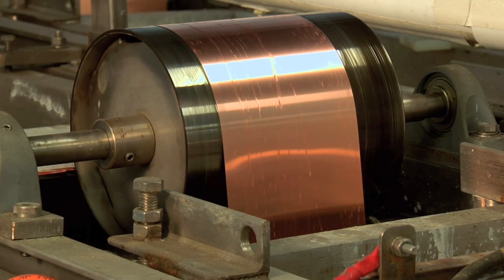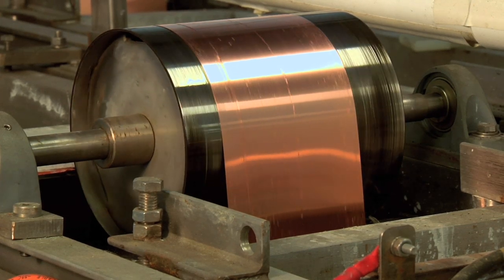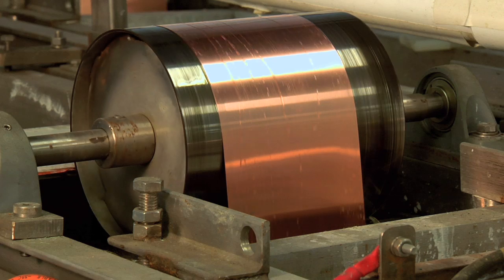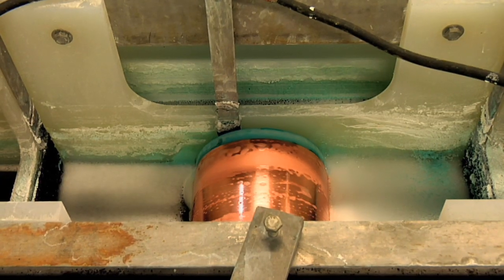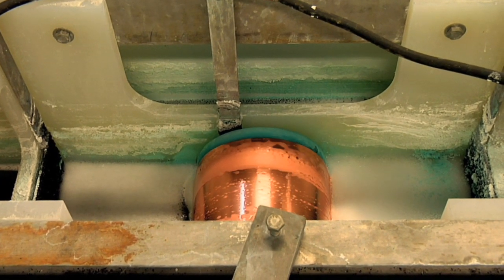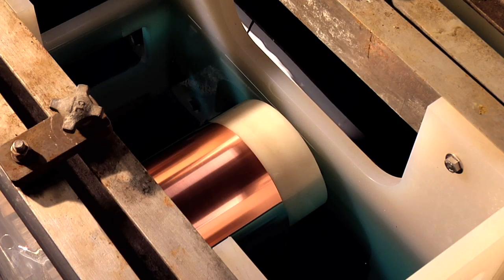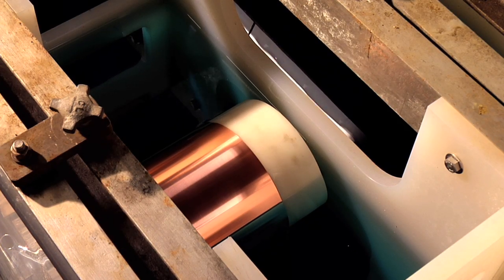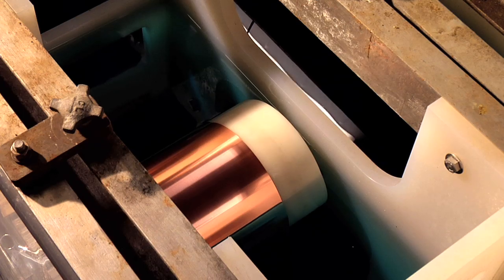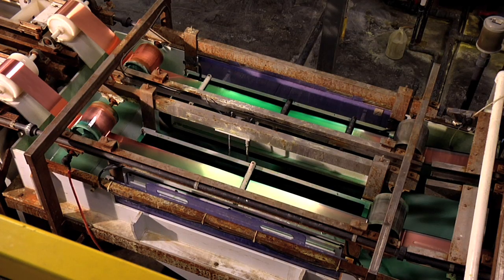Stage 1 is a de-smut immersion solution that is an alkaline cleaning agent. Stage 2 is a galvanic electro-clean solution making use of anodic cleaning procedures. Stage 3 is an immersion acid activator solution that allows the subsequent crystal clear coating to adhere to the copper strip.